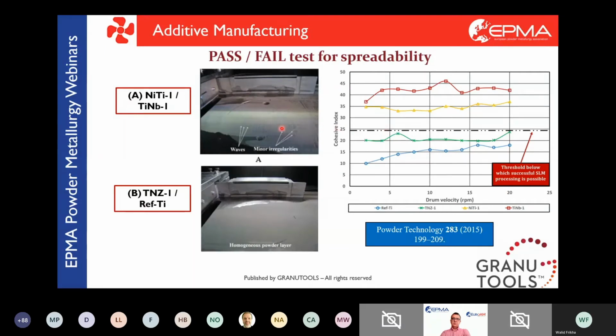On the left side you have 2 pictures from a test bench. Picture A is not having such a good powder layer - there is some wave, some irregularities, which could lead to a bad final part. This is what we don't want. On the bottom, we have a very homogeneous powder layer, which will lead, we hope, to a good piece. This is what we want.